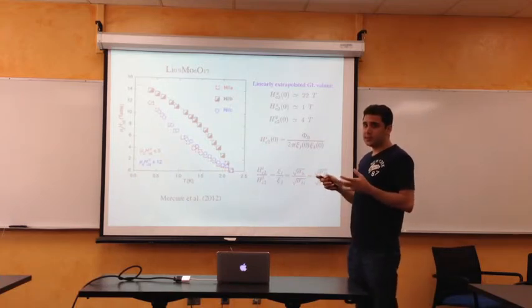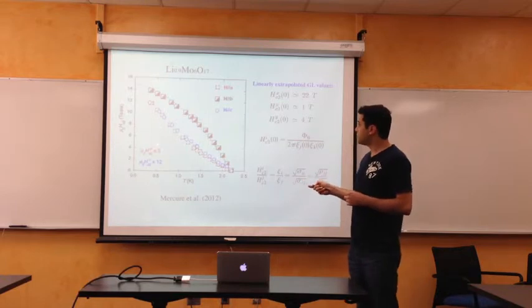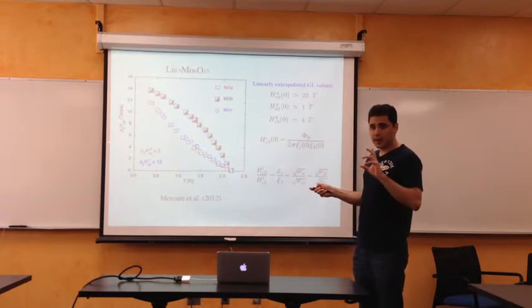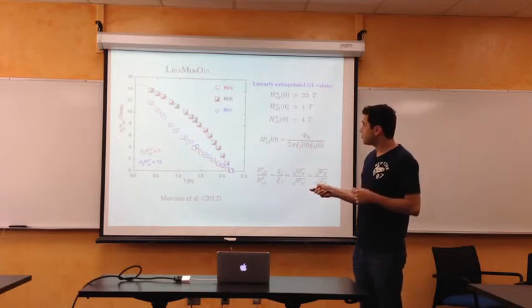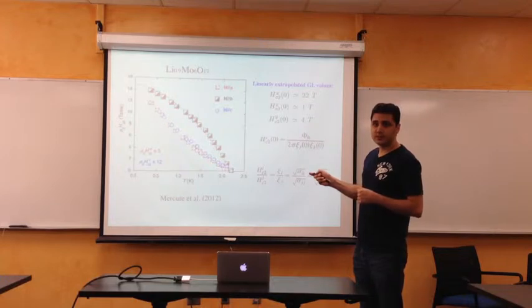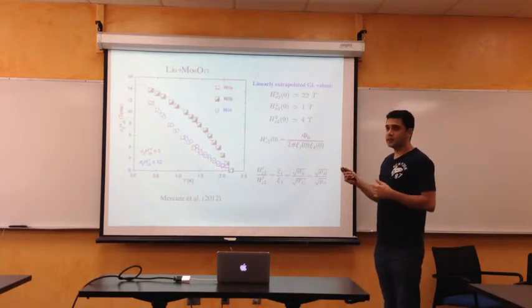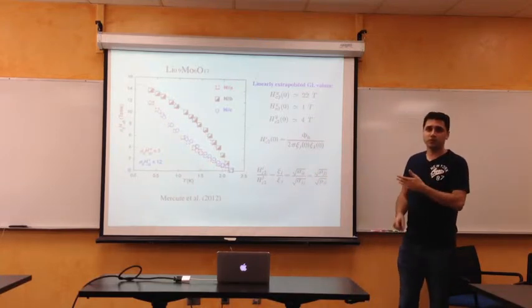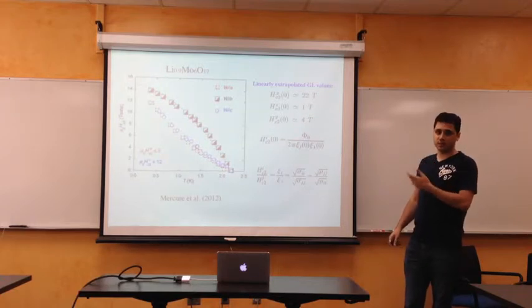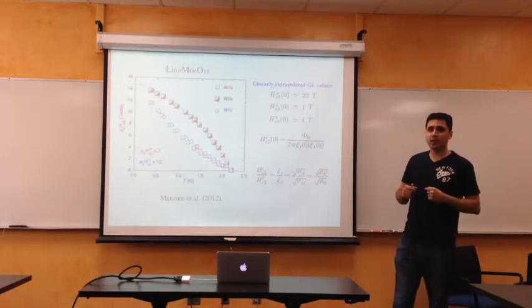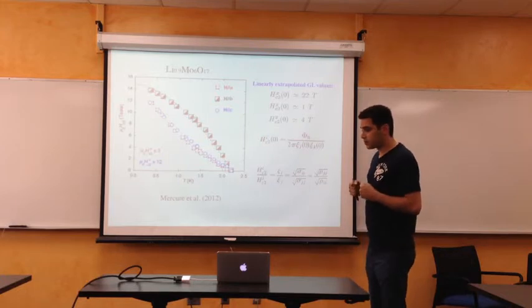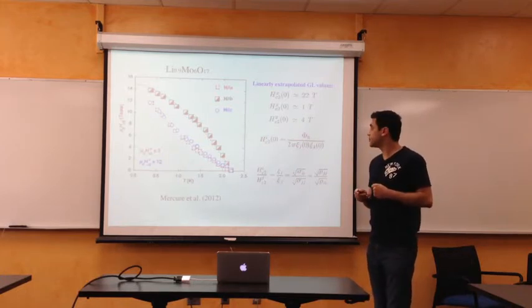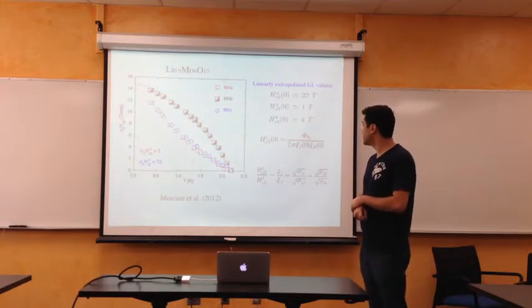So if it was a singlet superconductor, we would expect superconductivity to be destroyed by Pauli effects around 3 Tesla, yet the field is all the way over here. So that presents a question, and we put forward this compound as a novel candidate for this rare phenomenon of triplet pairing in unconventional superconductivity.